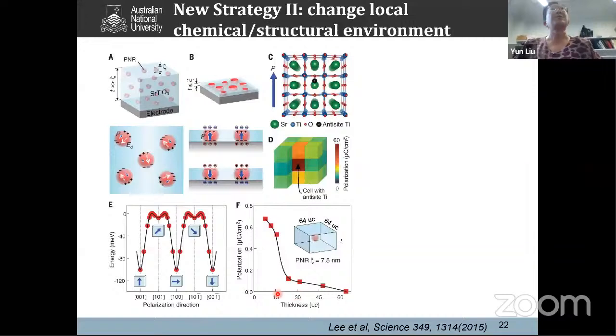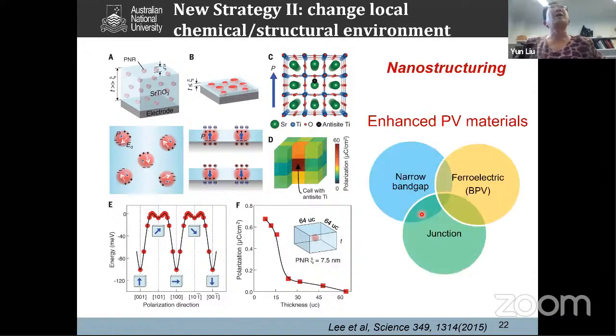Okay, so based on this strategy, we have recently done certain work trying to nanostructure the materials, to enhance the photovoltaic properties. So maybe later this afternoon you will see a lot of work done on the hybrid perovskite. Okay, so what I want to do here is, generally, semiconductor photovoltaics use narrow bandgap semiconductors to form the junction and give you photovoltaic effects. So you can excite the electrons, and the photocurrent is quite large because of the narrow band gap, but the photovoltage is very low because it is limited by the junction or barrier height.